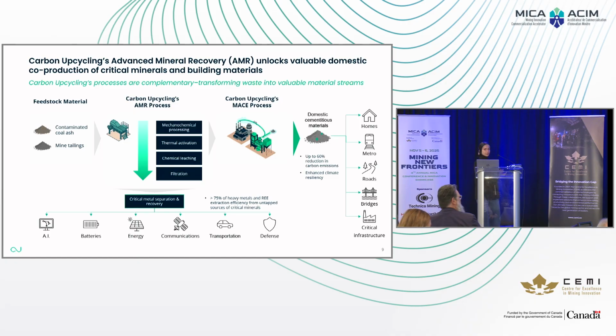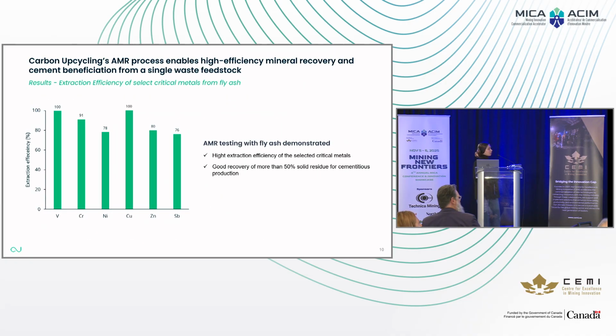So we have dual benefits here: the critical elements recovered as a solution, and also the residue that is aimed to be used later as supplementary cementitious material. Our process allows us to recover more than 75% of critical metals, among them vanadium, chromium, nickel, copper, zinc, and so on. It also allows us to recover more than 50% of the solid residue, to then be used